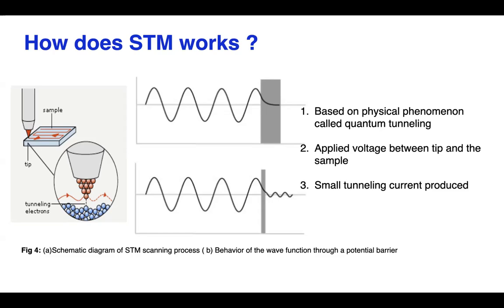So when the thickness of the vacuum barrier is very small, then the electronic wave function can tunnel through the barrier and we can get some information. This results in a tunneling current from tip to sample, which depends on the bias voltage that we apply between the sample and the tip.